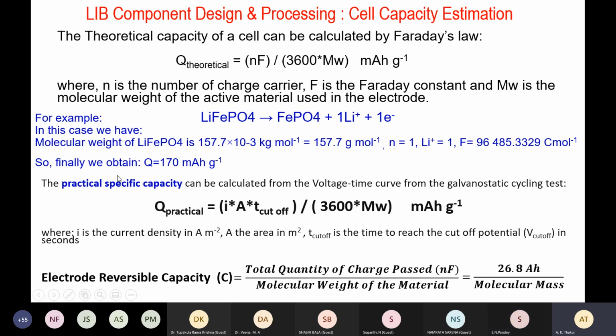It means if 1 gram of lithium iron phosphate is used in the design of a coin cell, it would be capable of delivering theoretically a cell capacity of 170 milliampere hour per gram versus graphitic carbon as the electrode or as the anode. And experimentally, the reversible capacity obtained has been to the tune of 130 to 135 milliampere hour per gram, which is ideally very good. In practice, we can calculate the reversible capacity of any electrode from the total quantity of charge passed by the molecular weight of the material, and this is the simplest way to calculate the capacity of a lithium ion cell.